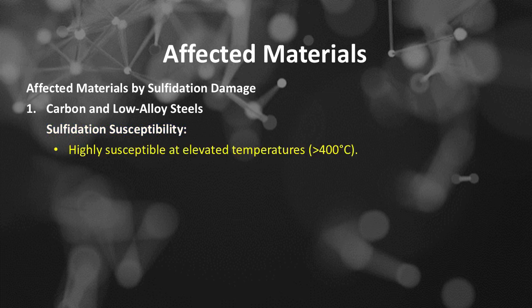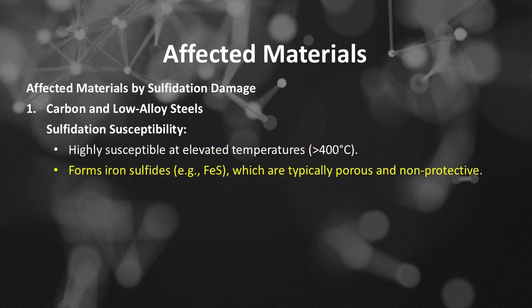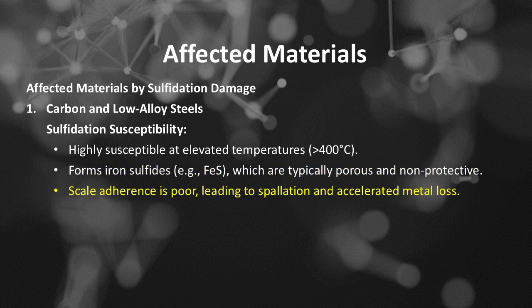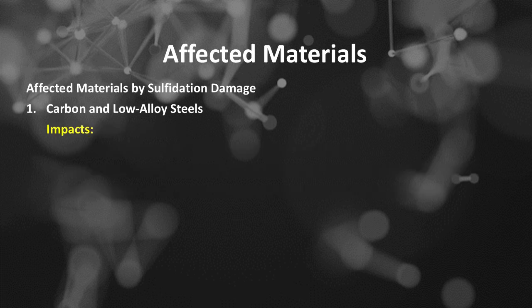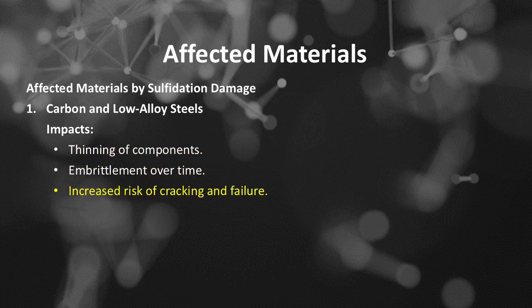Highly susceptible at elevated temperatures greater than 400 degrees Celsius. Forms iron sulfides, such as FeS, which are typically porous and non-protective. Scale adherence is poor, leading to spallation and accelerated metal loss. Impact of sulfidation damage on carbon and low-alloy steels. Thinning of components. Embrittlement over time. Increased risk of cracking and failure.